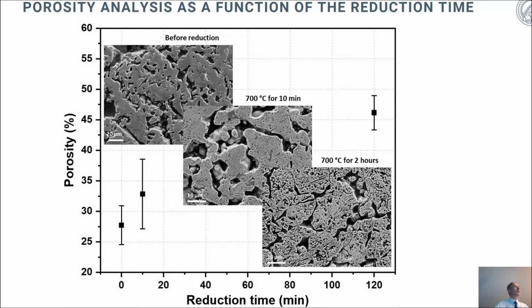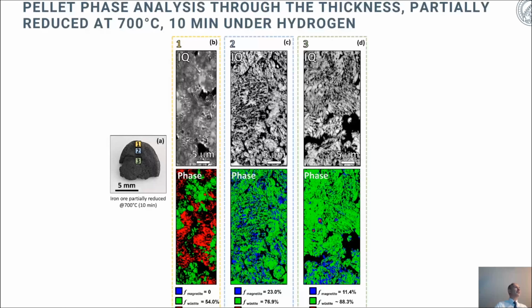Now, what is also interesting is to look at the development of the internal porosity as a function of the reduction time. This is shown here, and you have this inherited porosity that we have seen before in the pellet prior to the hydrogen-based reduction. And when you start reducing it, you see how the porosity, which is about 27% in the beginning, grows towards a value of more than 40%, which shows the difference of the acquired versus the inherited porosity. That means about 20% of the porosity is created during the reduction. And some of this is due to fracture, others are due to diffusive porosity growth.